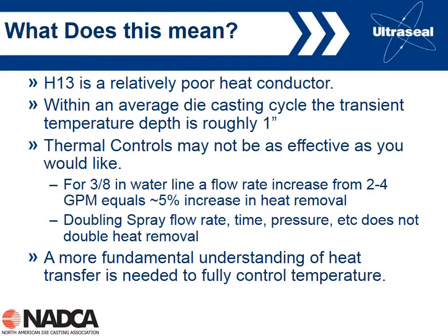So for example, for a 3/8 inch diameter water line, if we double the flow rate from 2 to 4 gallons a minute, all we're doing is getting a 5% increase in the heat removal. So changing the water flow rate had only a very minimal effect on the heat removal rate. And certainly, as we've just been showing with experimental data, doubling the spray rate, the time, the pressure, is certainly not doubling the heat removal rate. And so we have to have a more fundamental understanding of heat transfer.